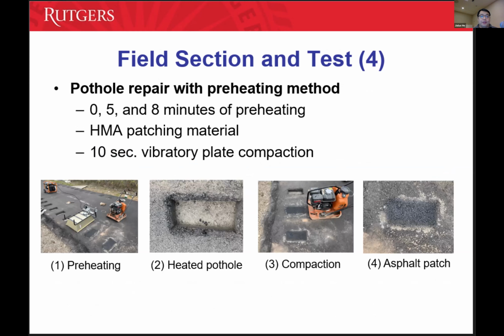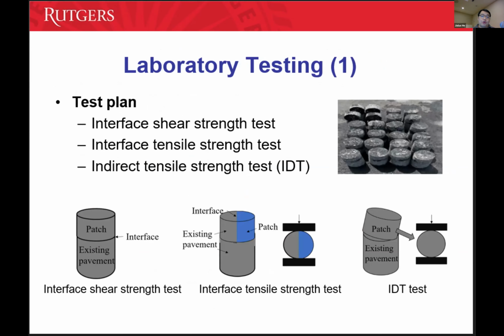So we select different times for the preheating, and we also use one patching material. And then after patching, we did a very quick vibration compaction. It's kind of like throw and roll, so with very little compaction. And then with the repaired patches, we also take the cores for testing. We try to look at what's the interface bonding.